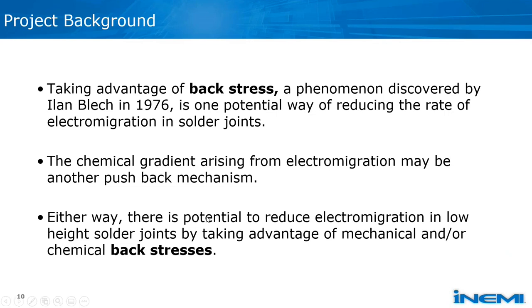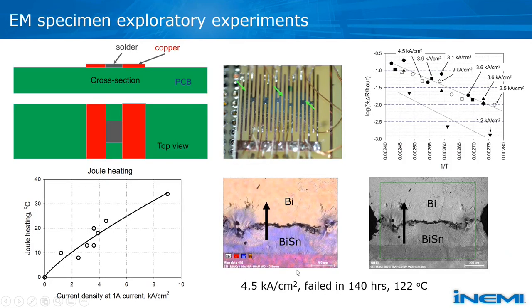So either way, there is potential to reduce electromigration when we have low solder joint height by taking care of the mechanical and the chemical back stress. So just to give an idea of some scientific experimental work we have done recently on tin bismuth. This is a simple but a very novel test we came up with. In the middle picture, this is the IPC test coupon we use for surface insulation resistance, and we are using this now to study electromigration.